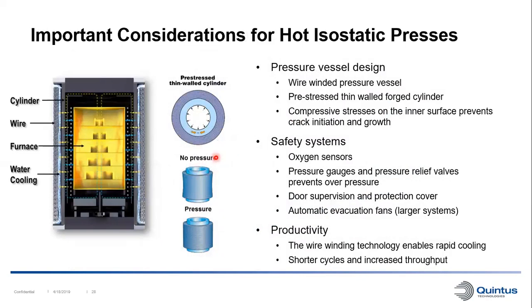So the inner diameter of our pressure vessel will actually decrease during the winding of it. And this creates compressive stresses on the inner surface, and this prevents crack initiation and growth for safety reasons. So even at maximum operating pressure, there will be only compressive stresses in the forged cylinder.